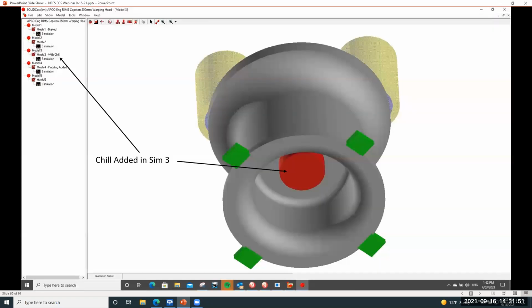This is just another view from the top. Just a couple of things showing here. I mentioned after running a first simulation, we weren't getting good feeding all the way through. In other words, the feeding zone was separating out. This shows an example of what I would call an intermediate model. That is, we're not showing an entire gating system, but what we're doing is we're adding the in-gate locations and making them out of fill material. By doing this, we can put hot metal in here without doing a rigorous filling simulation.